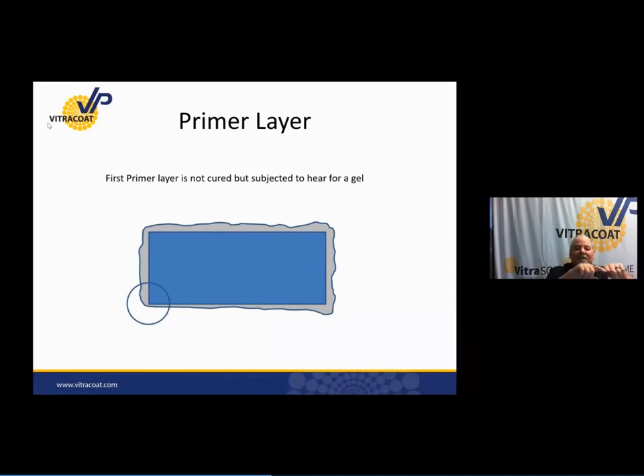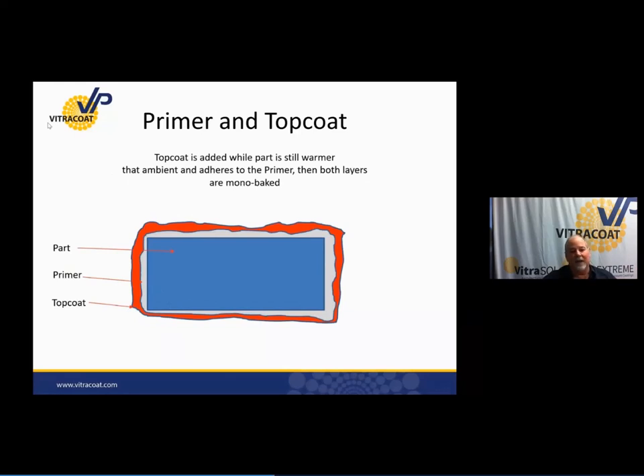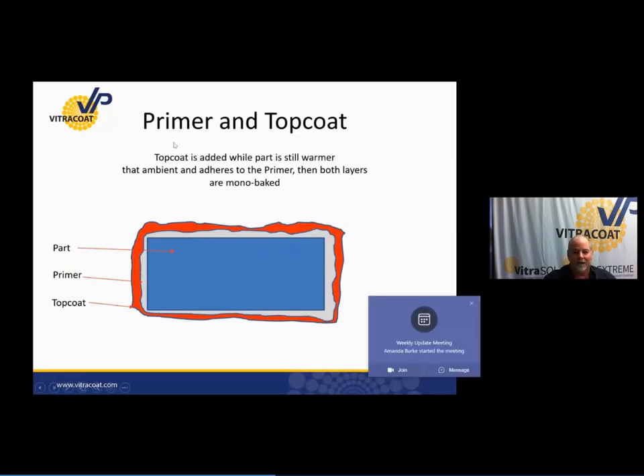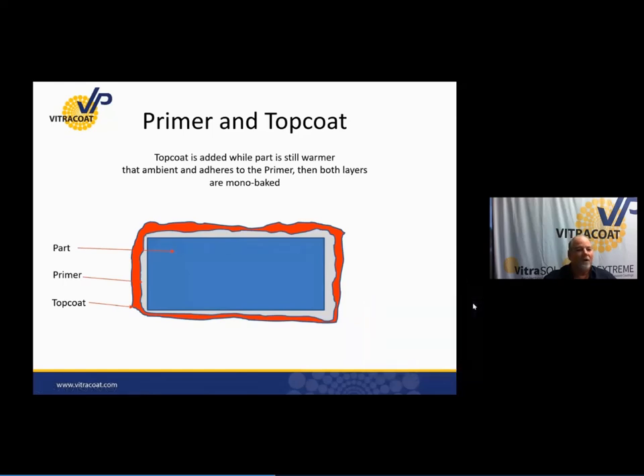But I have this layer of coating with a tacky film that's gelled before I put on my top coat. So I'm going to build better and I'm going to build thicker in my most vulnerable area with this 2-layer system. So I put on my primer and then I put on my top coat, which in this case is the red. The idea here is that I want to build where I'm most vulnerable again. I want to build on those edges. And so the answer, if you put on a single layer at 4.5 mils or a dual layer with a primer and a top coat, I believe your protection dramatically goes up with that 2-layer system.